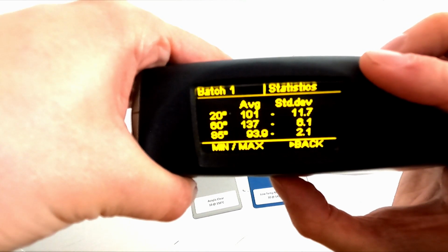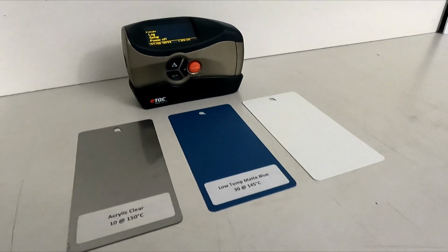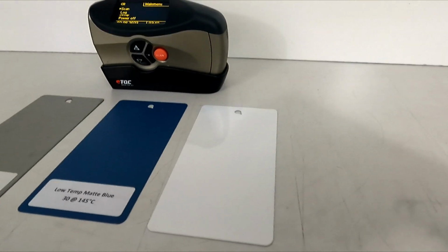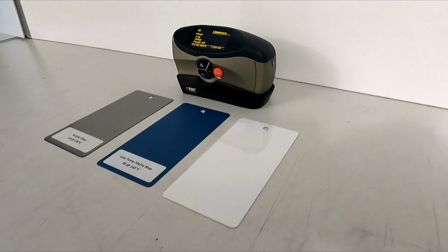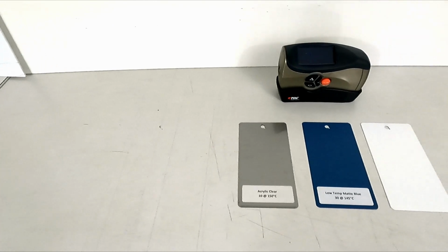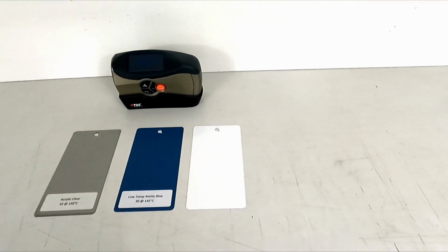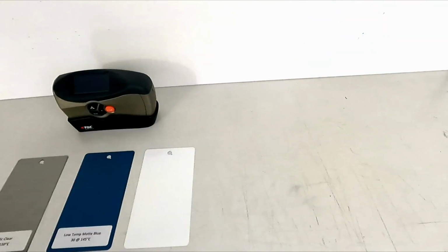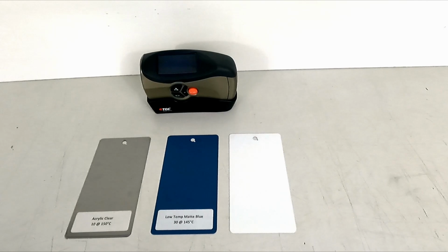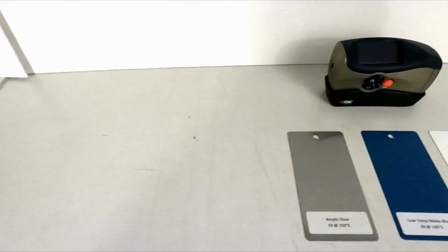In the event that the gloss is out of specification, some changes will need to be made. If you are an end user purchasing the powder, you will want to contact the supplier to let them know that the coating does not meet your specification. If you are a manufacturer of the powder running QA on a batch, you will need to determine if something changed during production which altered the expected gloss, for example, an improper weigh-up of raw materials. You may have to adjust the coating formulation, then check the gloss of the new batch to determine if it now meets your customer's specification.